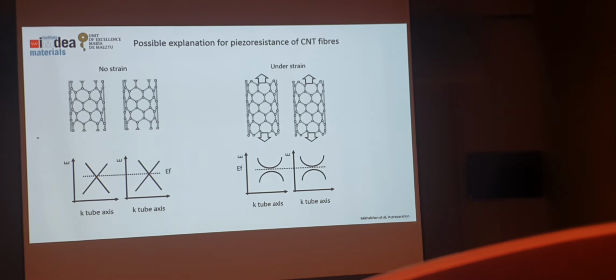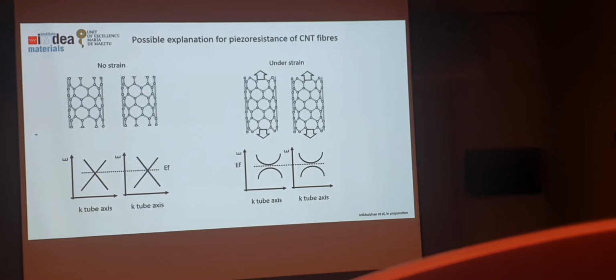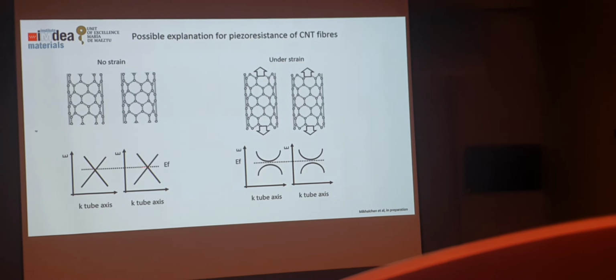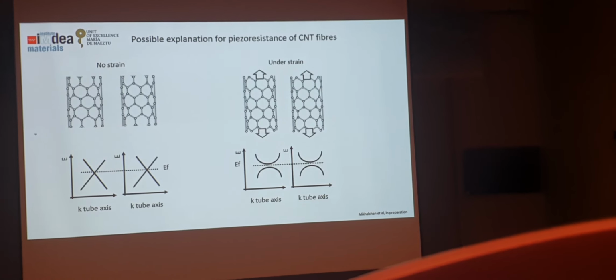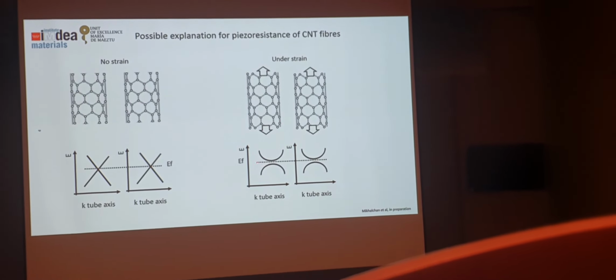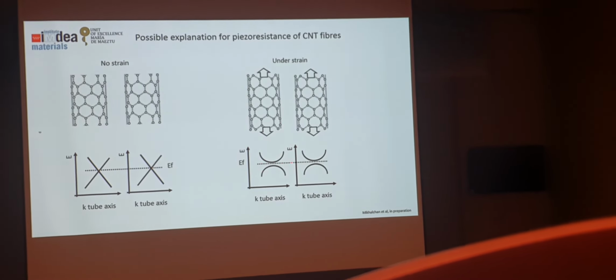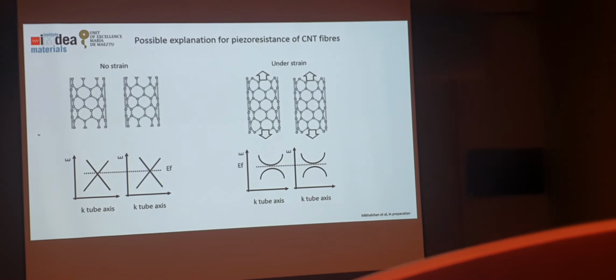But anyway, so with that insight, what I think may be happening in piezoresistance is essentially that what we're seeing is the effect on the tunneling resistance. So if you take nanotubes that have no strain, the Fermi level is probably close to here, and then if they are strained, a gap may perhaps open. But of course, the issue is the tunneling between the two tubes.